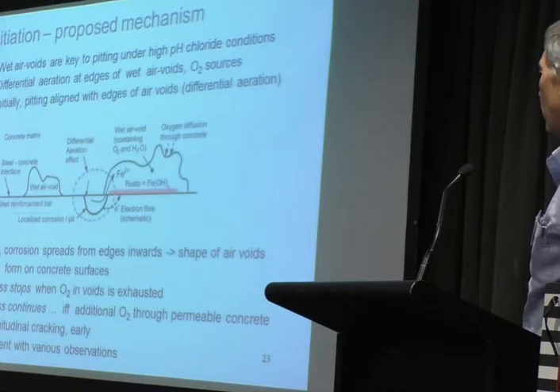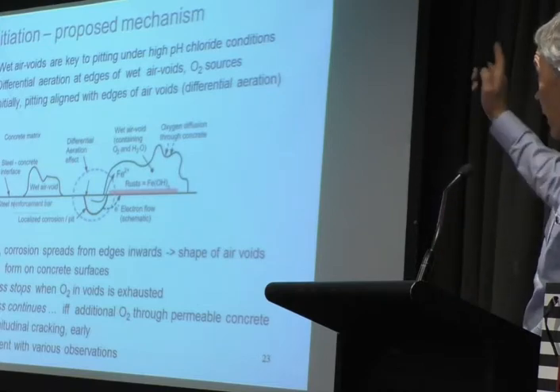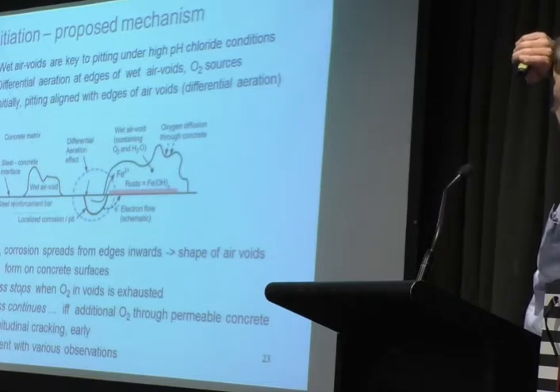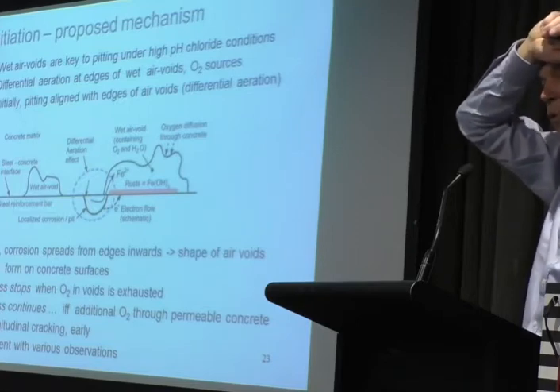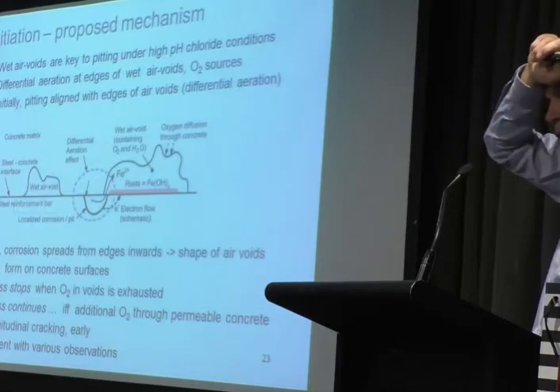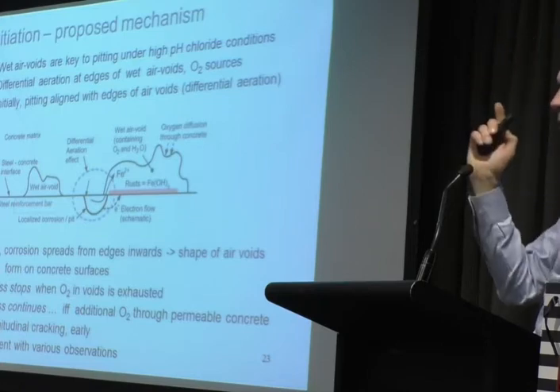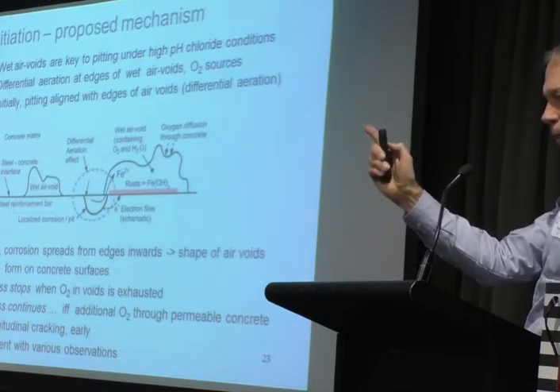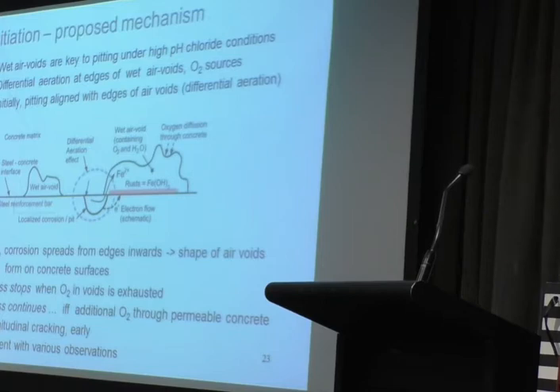So you can get longitudinal cracking, and we're now seeing in our worst concretes in our lab, after 13 years in the worst, lousiest concrete, very porous concrete, we're seeing a longitudinal crack. So we've now got to the stage where things are getting serious. But there are other issues.